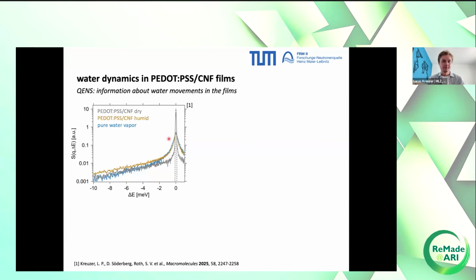And this is now our data. So this is called a dynamic structure factor as a function of the energy transfer. In this case, it's only the very first cycle. So we have a dry film, we have a humid film, and we have in blue pure water vapor as a reference or an empty cell measurement. You already see some differences, so something is happening there. That's always great to see when you are at the beam time and you see changes, then you know, okay, something's happening there. And we can do a little trick to make these changes a bit more visible.